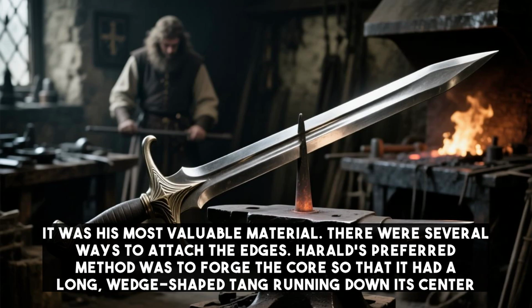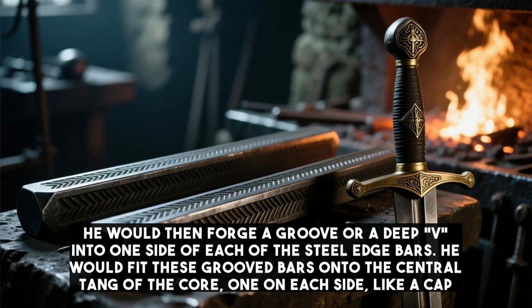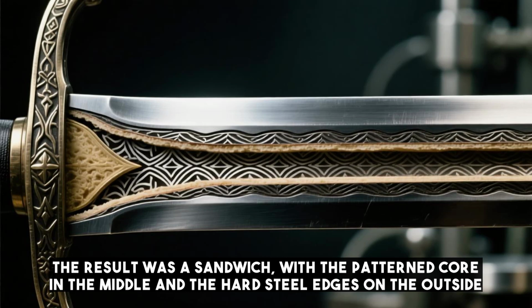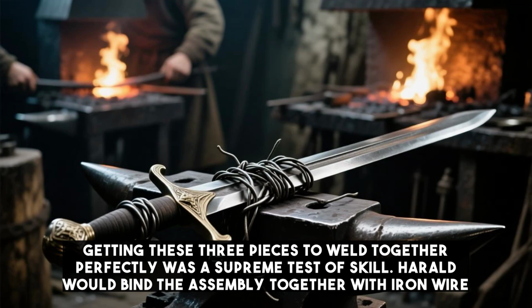There were several ways to attach the edges. Harald's preferred method was to forge the core so that it had a long wedge-shaped tang running down its center. He would then forge a groove or a deep "V" into one side of each of the steel edge bars. He would fit these grooved bars onto the central tang of the core, one on each side like a cap. The result was a sandwich, with the patterned core in the middle and the hard steel edges on the outside. Getting these three pieces to weld together perfectly was a supreme test of skill.